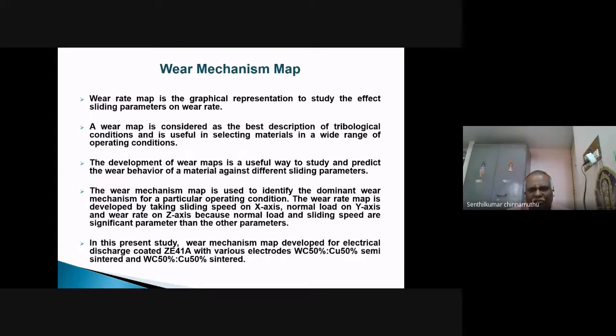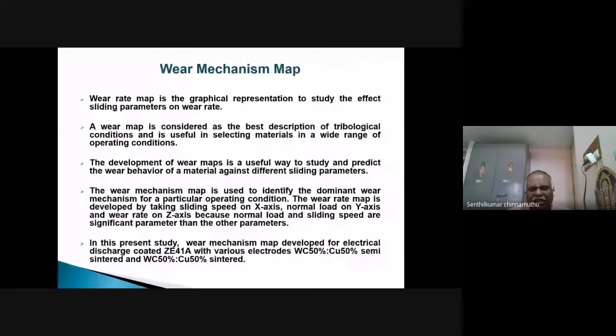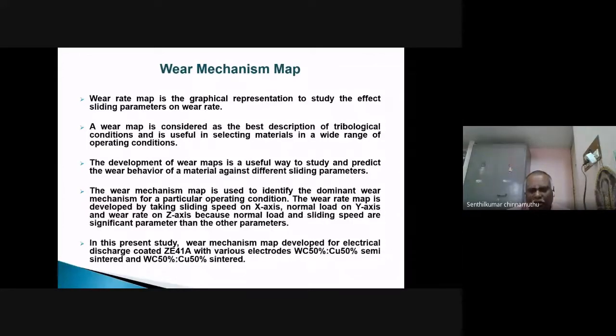The development of wear maps is a useful way to study and predict the wear behavior of a material against different sliding parameters. The wear mechanism map is to identify the dominant wear mechanism for a particular operating condition. The wear map is constructed taking sliding speed on the x-axis, normal load on the y-axis, and wear rate on the z-axis, because normal load and sliding speed are the most significant wear parameters compared to the other parameters. So in this study, you have to use 50-50% semi-sintered and 50-50% sintered material coated on ZE41, a magnesium alloy, electrodischarge coated magnesium alloy. The wear mechanism map for these two materials was developed.